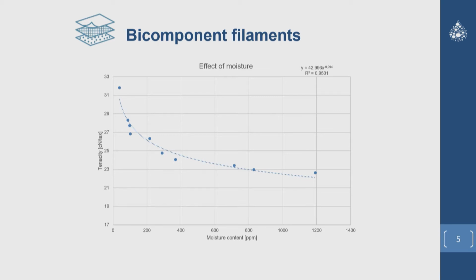So we did a lot of tests to optimize the materials. The first thing is that we investigated the effect of moisture. Why do we do that? Because we work with PLA. It's sensitive to hydrolysis, so you need to have a dry PLA material before you start. We did a test on what tenacity is reached depending on the moisture content of our PLA. Here we see if you dry up to 50 ppm, which is really dry, you can get a tenacity of 32 centinewton per tex in this case. Using the same parameters, but with a material that's less dry, you can see a clear drop of almost 10 centinewton per tex if you don't dry it. So for PLA, it's really necessary to dry it before you start. That's one of the main things you need to keep in mind when using this type of bio-based raw material. And then we started with the bicomponent filament extrusion.